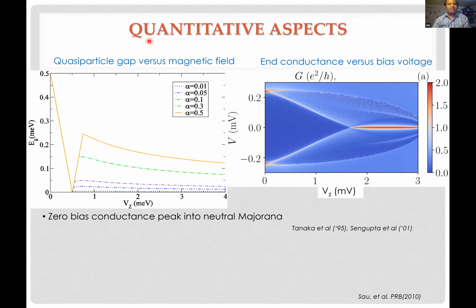Let's talk about the quantitative aspects of signatures. The first thing that I mentioned was there should be a topological phase transition. What that means is if I measure the gap in the middle of the wire somehow, the superconducting gap should close and then reopen. And the value of the reopen field depends on the spin orbit coupling. On the x-axis, I have the Zeeman splitting from the magnetic field. When I go past a critical value, this is the Majorana phase here. And in this phase, I'm plotting the end conductance, the tunnel probe conductance, and I should maybe see this gap closure.